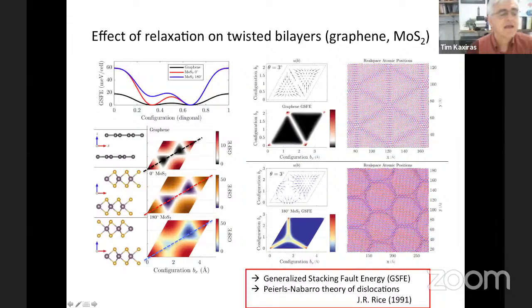The arrows represent the amount of atomic relaxation in different regions of the supercell. And this is a schematic of the relaxation. So black is basically no relaxation. At the center of these triangles, which are the AB and BA regions, there's no relaxation. But at the boundaries, there's a lot of relaxation, and especially at the corners, which are the AA regions. So using this, you can produce this pattern, and this includes full relaxation of the atoms. So you see these AA regions, these domain walls, and these AB or BA regions, the low energy regions, including the full relaxation of all the atoms in the graphene bilayer.